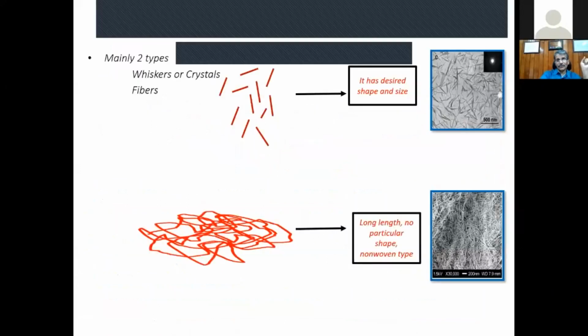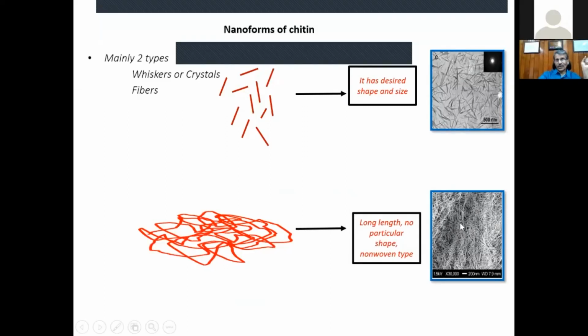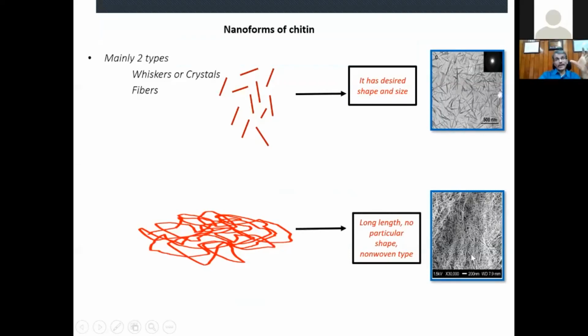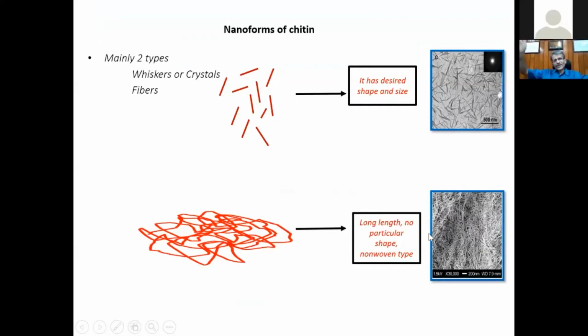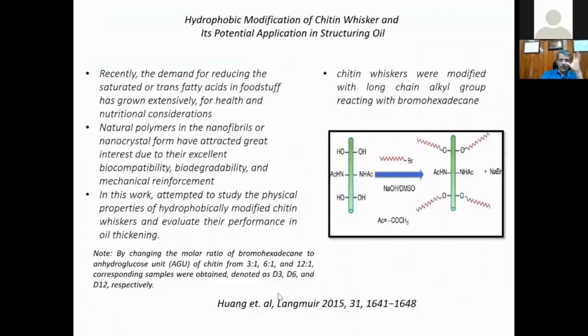after cellulose. Dear friends, one can make nanocrystals of chitin or nanofibers of chitin. If you use a strong acid, you get nanocrystals. If you use a weak acid, we get nanofibers. So it's a simple acid washing. You remove all the protein by washing. Let me show you one slide.